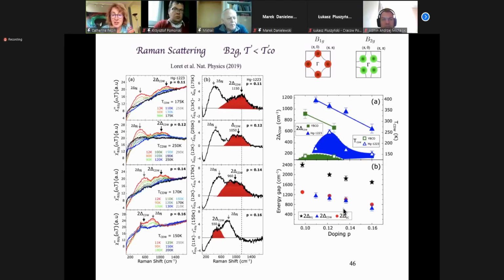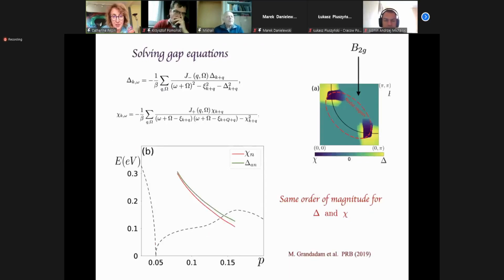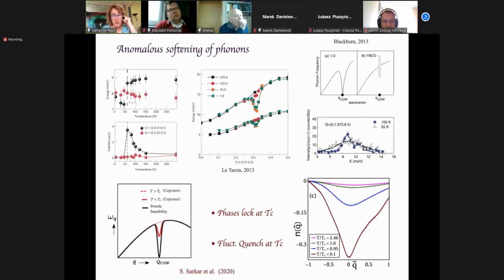Which goes very well with this idea of emergent SO2 symmetry, or these ideas of entanglement of the two orders of fractionalized pair density wave. Here is the scale that they attribute to the formation of the pseudo gap. So within our small model, we were able to get the two orders of the same order of magnitude. We can explain phonon softening, which is also super anomalous in this compound. So you see, when you have charge order, you usually see phonon softening below the ordering of the charge. Here is a typical example where the charge is ordering at this wave vector, and you see the phonon is softening at this wave vector. Here, the cuprate sees the phonon softening at the wave vector of the charge, but below TC, the superconducting one. It's a very nice phonon softening, but it's below TC and not T charge. So why? We got it within our model by saying that the phases are locking only below TC, and you have a lot of phase fluctuations above TC.